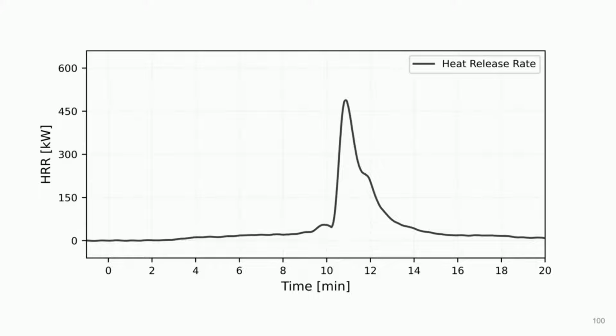At time 0, you will see that the line burner is introduced into the cladding joint within the experimental rig, and I'll show you a video of this in a moment. You'll then see that the polyethylene core from the ACM begins to melt and to drip into the drip tray beneath the ACM panel joint. After 4 minutes, you'll see that the line burner is removed, but that there is a small pool fire of burning polyethylene within the drip tray. You'll also notice that we leave the line burner burning. It's a bit distracting in the leftmost view that you'll see. There's a line burner there throughout, but it's pulled away from the sample in that condition.